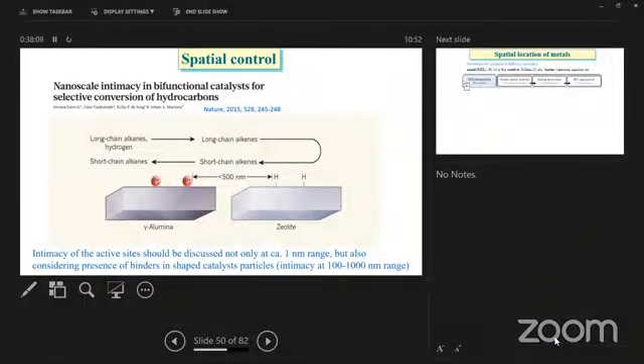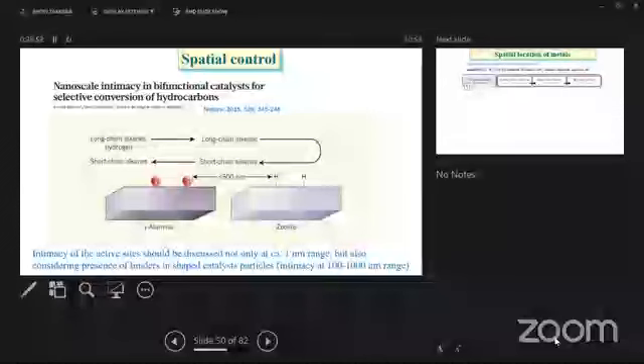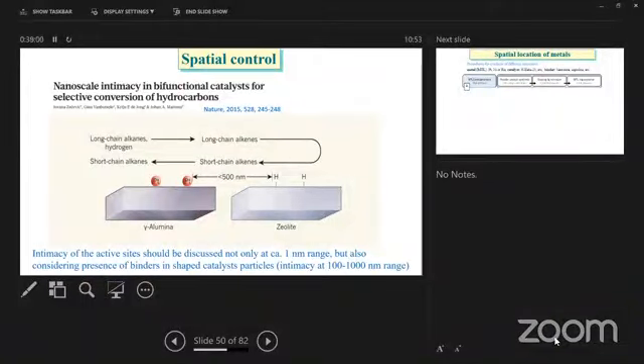Some years ago, well, already 9 years ago, Krijn de Jong from Utrecht and Johan Martens from Leuven published a paper about the nanoscale intimacy, and they were trying to challenge this concept. So, summa summarum, the conclusions were that the acid sites should not necessarily be close to the metal sites. Why is that? They put it schematically here. Platinum can be put on the binder. The binder is alumina, while the zeolite has different acidity. What was the idea behind the conclusion? If the sites are too close to each other, then you might have deactivation, formation of coke on the acid sites, and that might influence the metal.